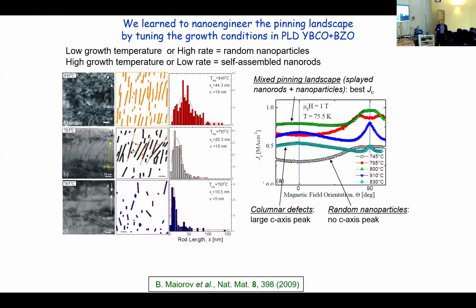The remarkable observation is that this intermediate situation, what we call a mixed pinning landscape, produced the best pinning. And that turned out to be a result that is rather general. It's a mixture of defects that produces the best pinning. And that is, to a large extent, the explanation of why the critical current of the YBCO films is so high.